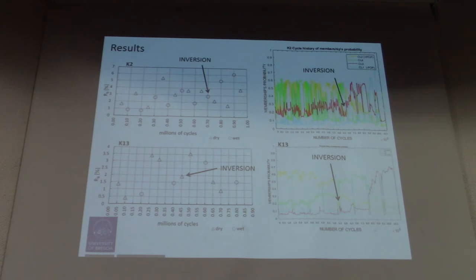You can see the results for test K2, in which the alternating dry and wet phases have a time length of 15 kiloseconds, and then the results for K13, in which the alternating wet and dry phases have a duration in time of 100 kiloseconds.